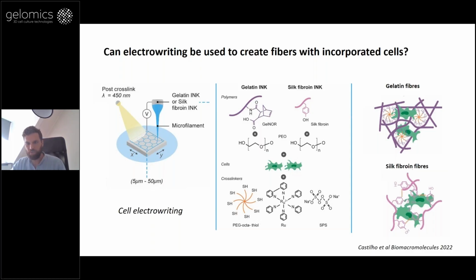And for the gelatin, we look at the norbornene-modified gelatin that can form a hydrogel through step-growth polymerization in the presence of, in this case, a multifunctional thiol-ene crosslinker, and unmodified silk fibroin that undergoes quick photochemical crosslinking due to the presence of tyrosines in its protein structure. And we also accelerate the crosslinking reaction, because it's paramount if you want to print with living cells that you have a quick crosslinking reaction.